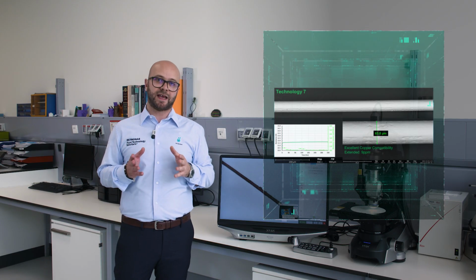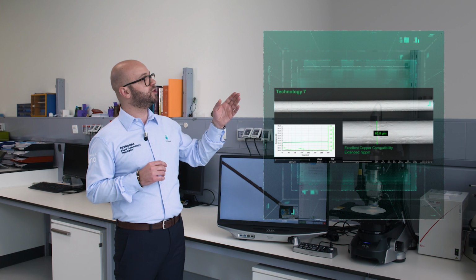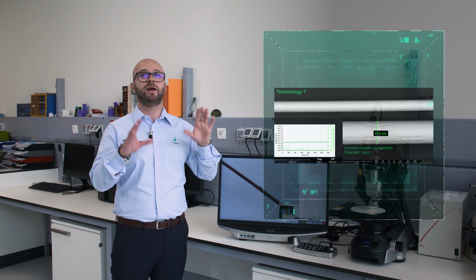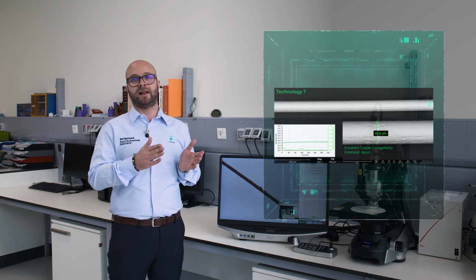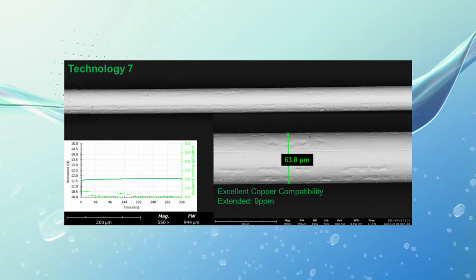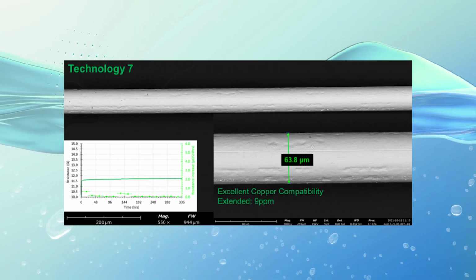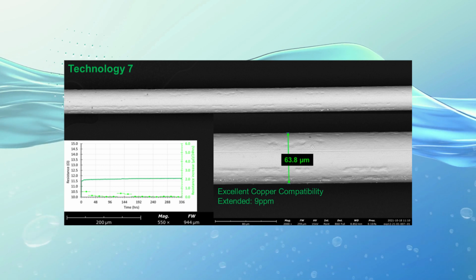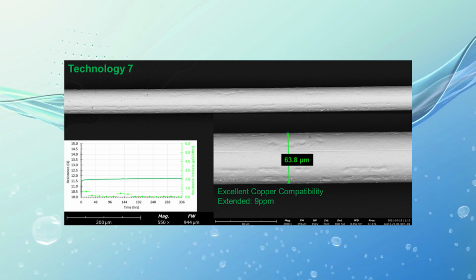For technology 7, the situation is different. We have a homogeneous dissolution of the wire that brings the wire to a final thickness of 63 micron. So, a very smooth, homogeneous corrosion phenomenon.